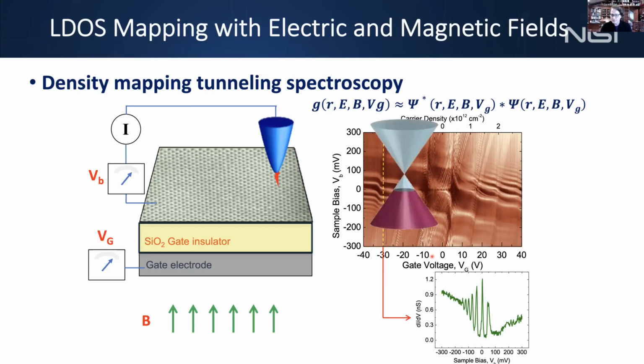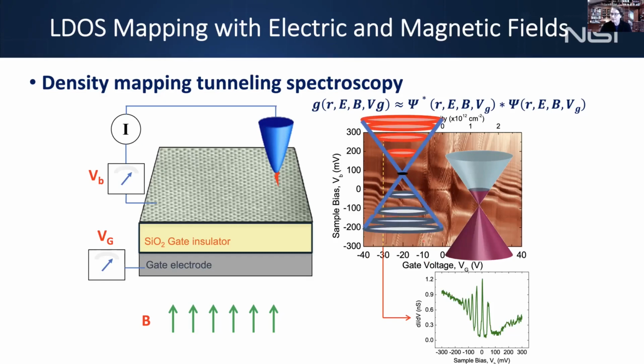So at negative voltage, we have hole doping. The Dirac point is above the Fermi level, so it's hole doped. And then as we go across here, we're increasing the doping level till eventually we get to electron doping. So that's why all the features go down in gate voltage, because the Dirac cone is shifting down. So here we have electrons filling up here. And this is what would happen in a bias versus gate map. The other thing is we turn on a magnetic field that quantizes the levels into highly degenerate Landau levels. And we can see that, for example, if we pull one spectral line out of here, we can plot that spectrum and we can see the Landau levels.